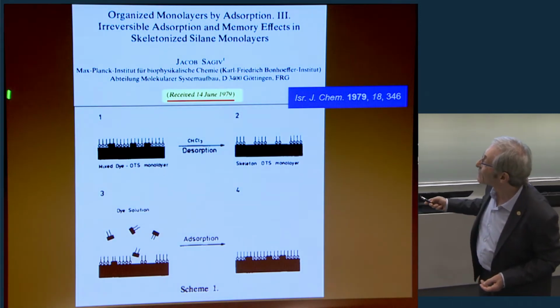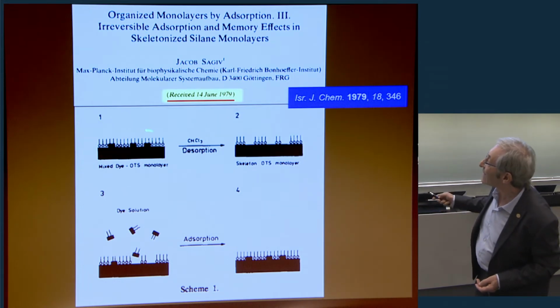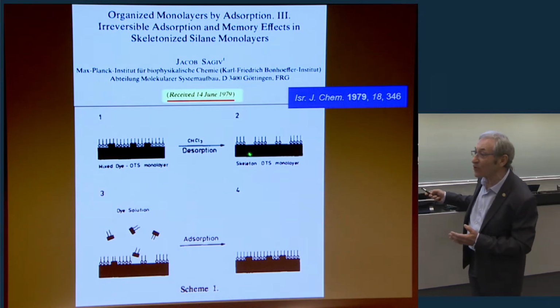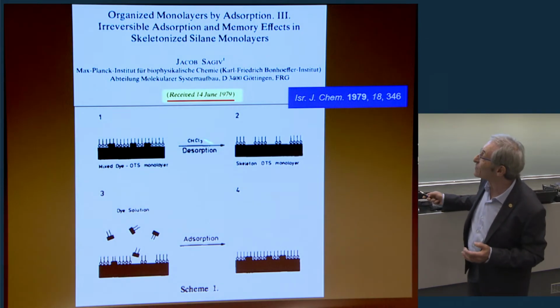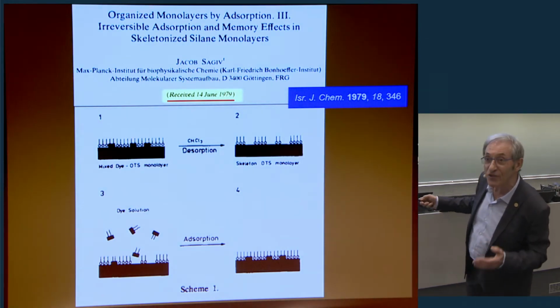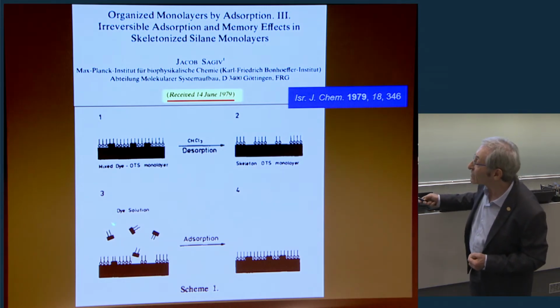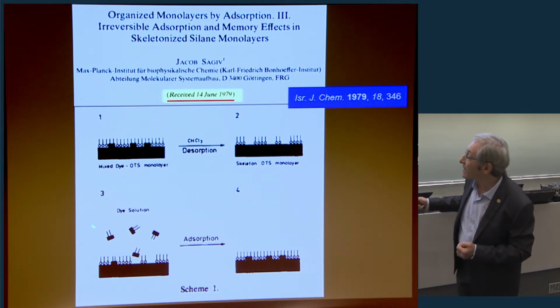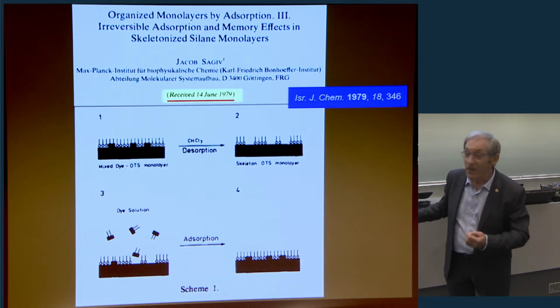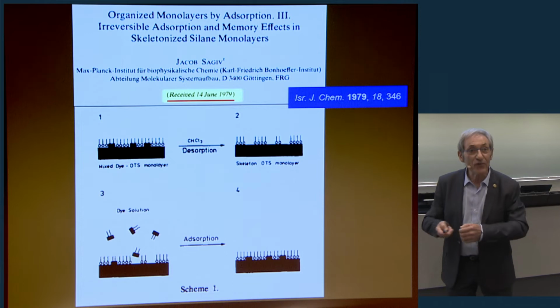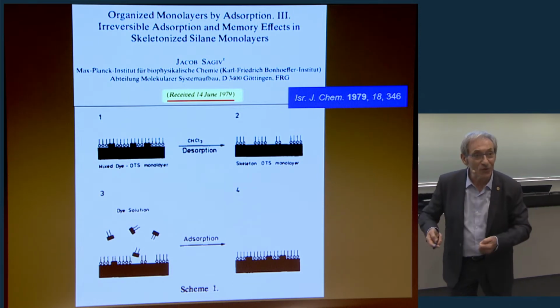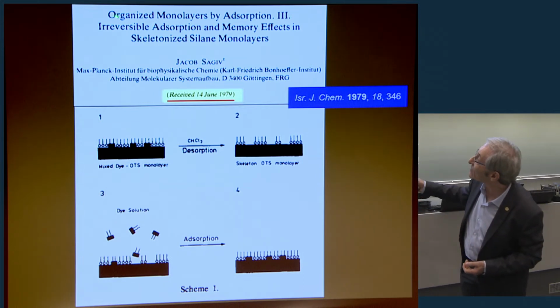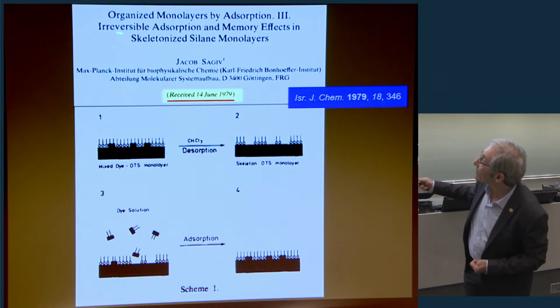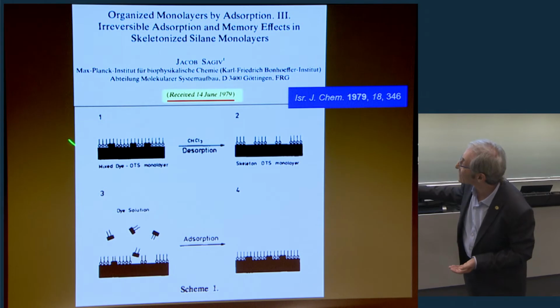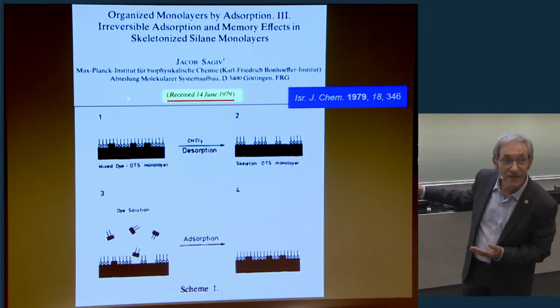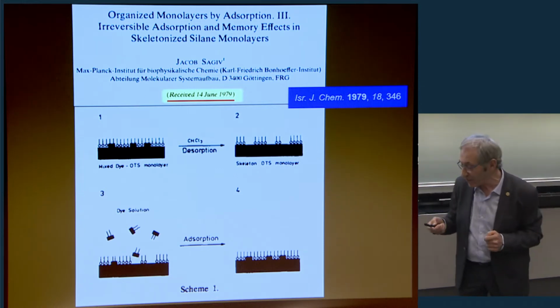And what was done here, this is a mixed monolayer. We have OTS together with a long-tail dye. The dye can be dissolved from the surface. The OTS monolayer sticks to the surface and cannot be removed. So it was possible to create molecular holes that have a memory of the shape of the dye molecules. And then dye molecules can be readsorbed in those holes, since the dye would not stick to the outer surface, only into the holes. If you have a dye that fits into the holes, it would adsorb. If you have a dye that has a shape which is bigger than the hole, it would not go into the hole. So this led us to create surfaces that exhibit memory effects, and we call them skeletonized silane monolayers, because you start with a mixed monolayer, you create here a skeleton monolayer with the holes that preserve the memory of those molecules that are taken away.